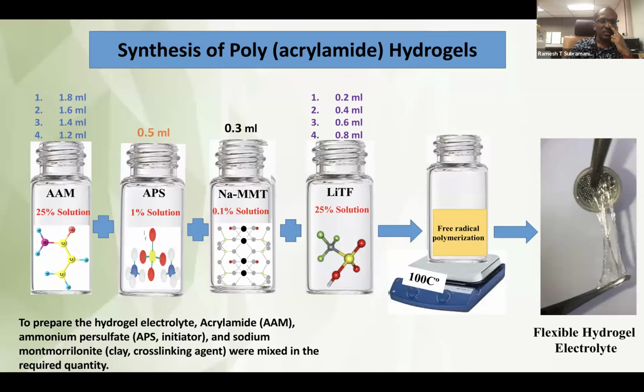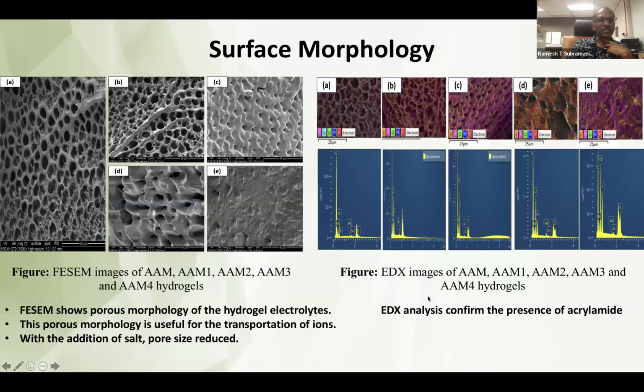Here are some of the results. You can see a polyacrylamide hydrogel, to which we add ammonium persulfate initiator and sodium montmorillonite, the clay, as a cross-linking agent. On the right hand side, you can see the flexible hydrogel, how sticky the material looks. And here are some of the FESEM results.